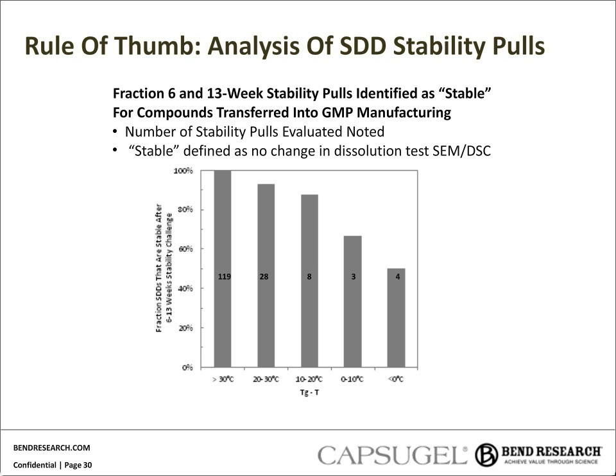And if we take a look at our historical knowledge of using this kind of rule of thumb, here shown in this histogram, on the y-axis we have fraction of compounds that are stable after a 6 to 13 week stability challenge as a function of the delta between the TG and the storage condition. And you can see that anywhere above about 20 degrees C difference, we rarely ever see an issue, and probably in those cases where we did, I might challenge that we didn't start with a homogeneous SDD. But as you get closer to the 20 to 10 to 0 delta between storage condition and TG, we start to expect to see issues.